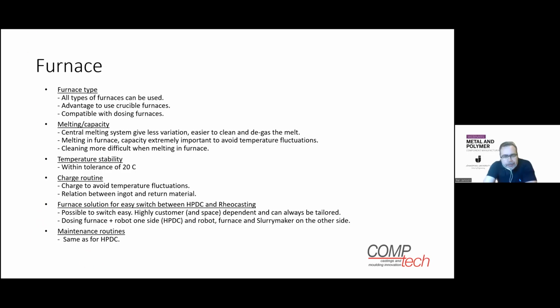One solution then is that you can keep the conventional high pressure die casting melt handling on one side of the shot end, and on the other side of the shot end you implement the Rheo process, including also metal handling for that type of alloy. Depending, of course, on how many changeovers you're going to do, I would say the extra investment of another furnace might pay off, otherwise you will have long setting times in between the two processes. Maintenance routines, I would say, are the same. It's important that you clean out the furnaces and scrape if you have a thermos type of furnace, so you don't get oxides and things like that in the furnaces.